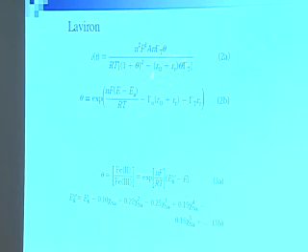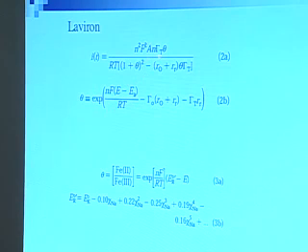That is these R's. The theta is your normal sort of Nernstian thing. But she throws in these R's, which are a nearest neighbor interaction for the oxidized species, and the R sub R, nearest neighbor interaction for the reduced species. Gamma sub T is the total concentration of molecules on the electrode surface. And so this is a nearest neighbor term down here that's modifying the overall Anson type result. It also turns out it affects the potential of the redox process, and it shows up here. And I actually meant to take this out of this slide, so we'll just ignore that. That's something we did for another thing that you can see later on.